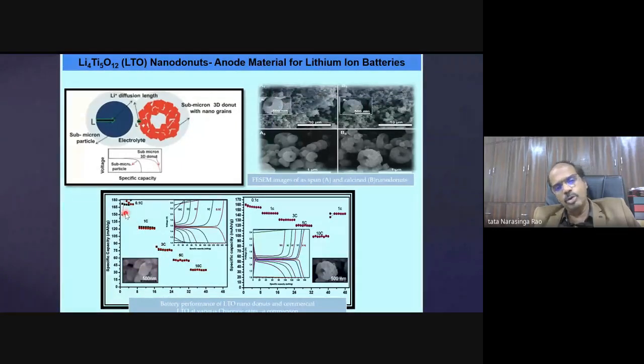That means as I go to higher C rates, 10C, the current dumped is so high. So if you can see here, it is an imported material with donuts, and what my student has made: at 10C rate, it's only 35 milliampere hours per gram specific capacity, whereas the donuts my student made is 100. So it's almost 3 times higher, even at very high fast charging and discharging rates. That's what LTO, I'm talking about LTO. So we could show that the size of the nano and the shape makes a difference for the charge discharge properties.